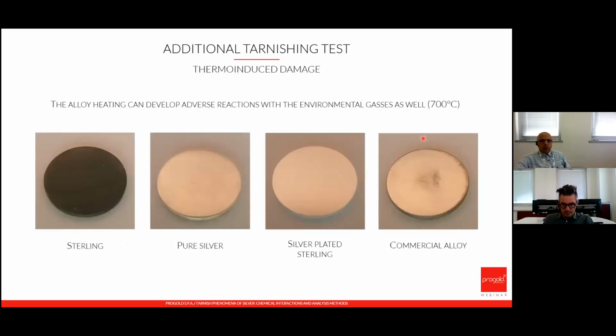And finally, to complete the study, the effect of temperature on the alloys was evaluated by heating the discs at 700 Celsius in air for increasing time, up to 6 hours, and examined under scanning electron microscope and by means of plasma emission spectrometry to collect morphological and elemental information and gain a closer understanding of real phenomena.